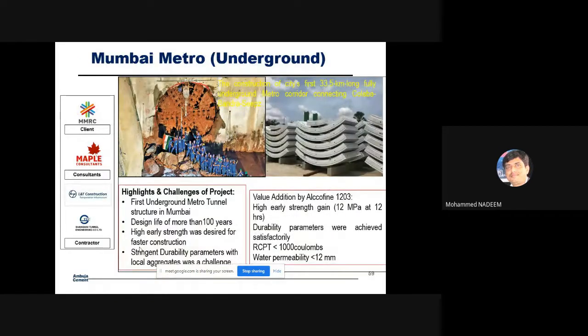Again, this project is going on in Mumbai, the underground metro projects. Again a very aggressive environment, and their requirement was early high strength. They were expecting 12 MPa in 12 hours, because this is an underground metro tunnel, and these liners are made of precast concrete. On the right side are liners; 6 pieces of these liners make a complete circle. The molds are very costly, so they were looking for early high strength of 12 MPa in 12 hours, RCPT less than 1000 coulomb, water permeability less than 12 mm, and a design life of 100 years.